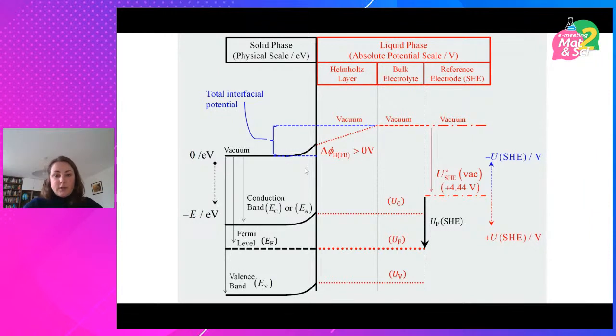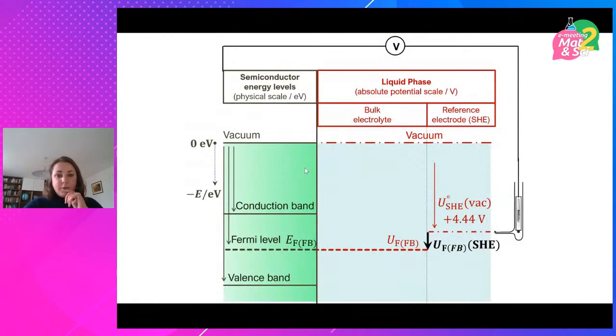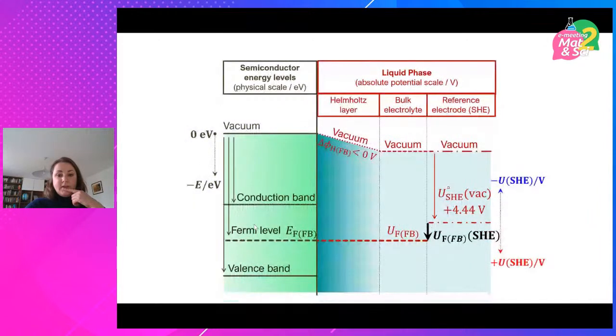in the results. So what I wanted to very quickly recap is how these experiments are done, right? What you're doing in an electrochemical experiment in the typical 3-electrode setup is using a reference electrode to measure the Fermi level of the semiconductor. So that's what you're measuring. That value changes when you have an offset in the Helmholtz layer, right? And then on top of that, so this is at the flat band condition. And then on top of that, you start to interfere. When you apply a potential, you start to modify the band bending, right?